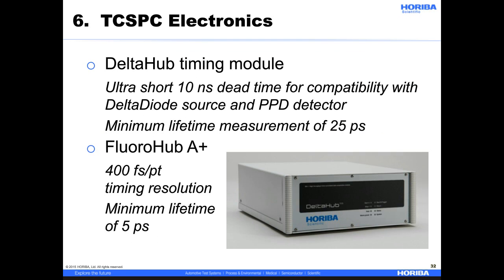While there are several options for TCSPC electronics, the Delta Hub timing module was used in this case. The Delta Hub has an ultra-short 10 nanosecond dead time and is fully compatible with a Delta Diode source and PPD detector. The minimum lifetime measurable with the Delta Hub is 25 picoseconds. Although not used in this set of experiments, the FluoroHub A+ is another option which has the best ultimate timing resolution at 400 femtoseconds per point. This extends the shortest possible lifetime measurement down to 5 picoseconds when used with an MCP PMT.